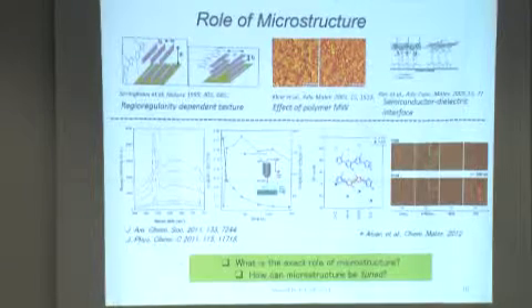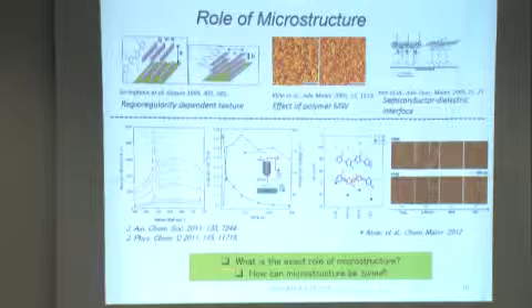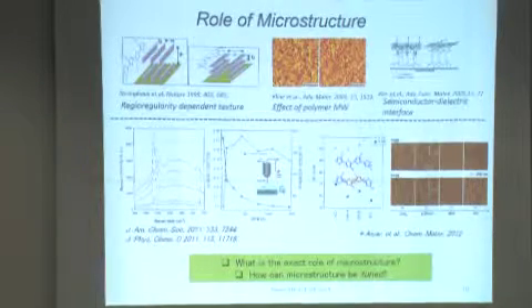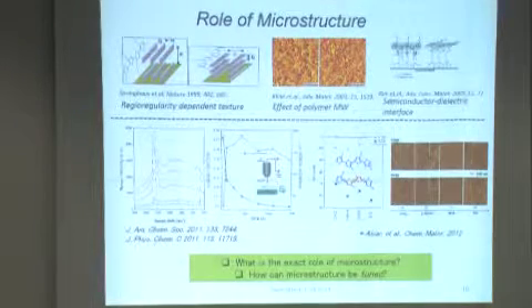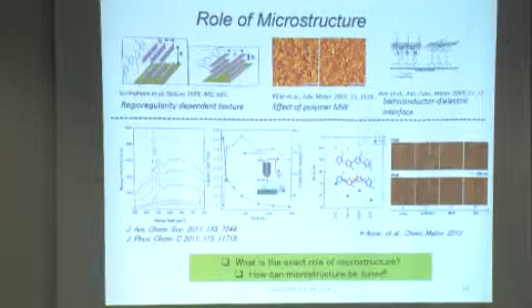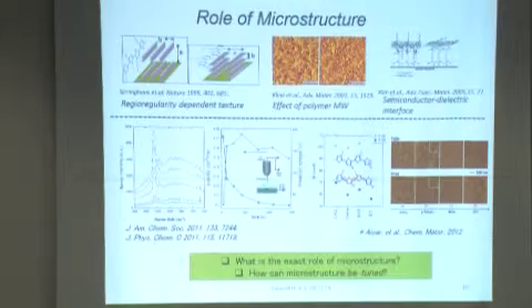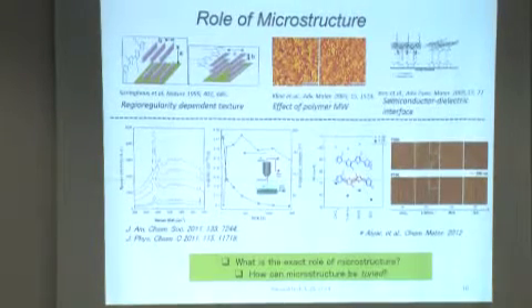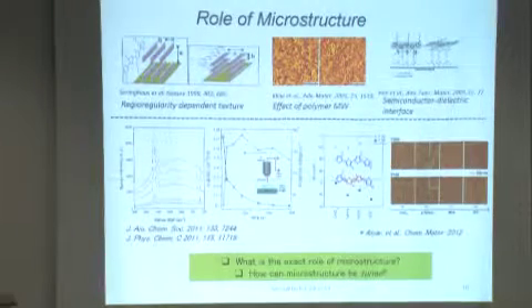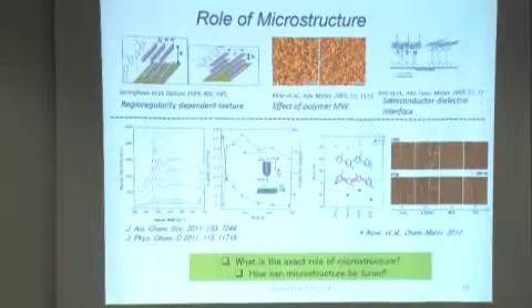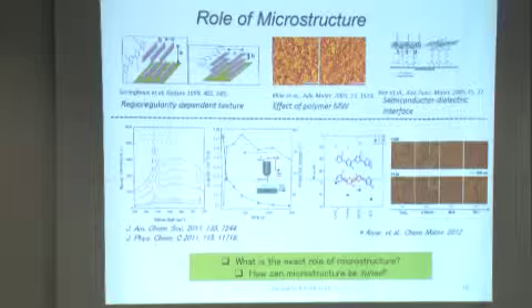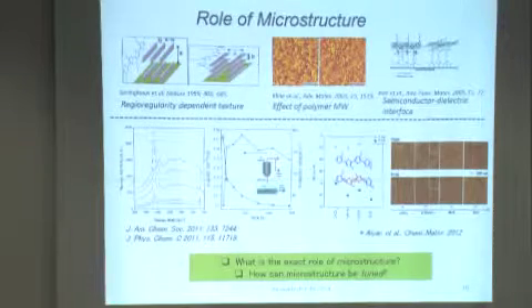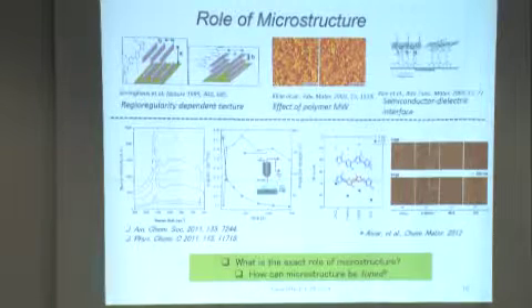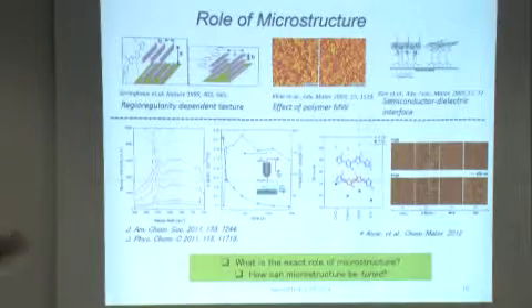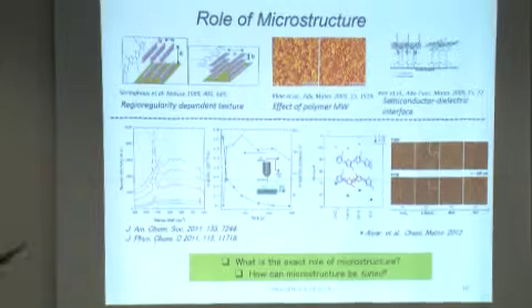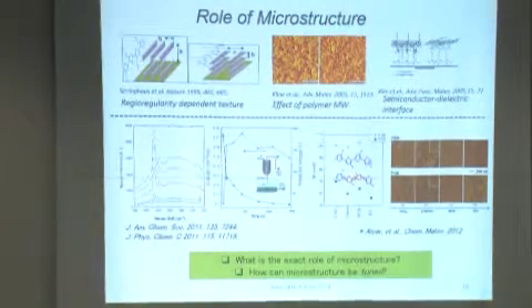So we started looking at poly-3-hexylthiophene to try to understand the role of microstructure and how we may be able to tune that microstructure using processing, and then also in situ techniques to look at solvent evaporation, or the evolution of solvent from a thin film, and look at what's happening to the polymer during that process. What I'll be talking about now are some results that we've published with David Collard and my student Avi Ayar a year or two ago, and also a collaboration with Mohan Srinivasarao in materials science, looking at the in situ studies with Raman of what's happening to the polymer chains as solvent is evaporating.